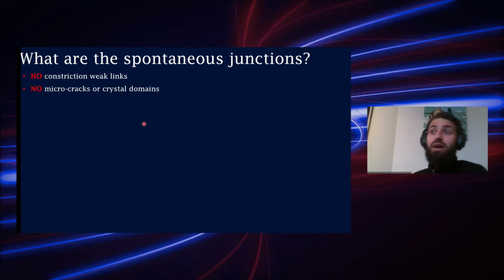You could also say it's microcracks or crystal domains, but this is not consistent with the fact that we obtain very high residual resistivity ratios and very sharp transitions. And also under inspection under the SEM, we don't see any inclusions or whatsoever.